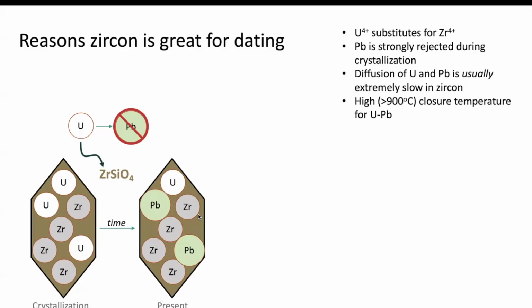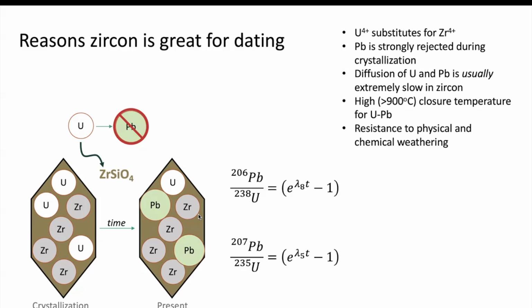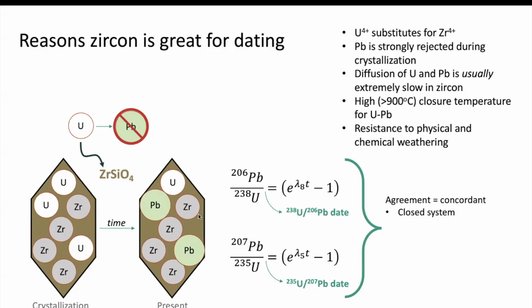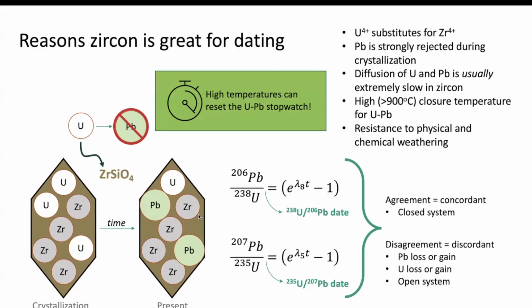There are some geologic processes that heat zircon up above that and disturb the isotopic clock, but there's not that many. So if we kind of know the history of the rock, we may be able to get a good date. And this is a really common technique that's used. Zircon is also really hard to physically and chemically weather. And since there are two different significant isotopes of uranium that are incorporated into zircon when it crystallizes, and they each break down into a different isotope of lead, we can measure all of those and we can get two different uranium lead ages. That is better than one. If we have two, we can see if they agree or not. So if they agree, that's called concordant, and much of the time we can say that it was a closed system, not always. When the two ages disagree, this is called discordant. And this can signal that there was an event or multiple events that disturbed the zircon and caused it to behave as an open system. Overall, that makes melt-grown zircon really good for dating since the high temperatures reset the uranium lead stopwatch.